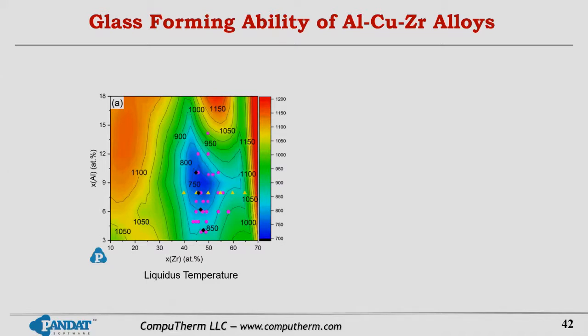Here, in this aluminum-copper-zirconium ternary system, we calculated the liquidus temperature for several hundred alloy compositions and presented the simulated results as a color map of liquidus projection, liquidus temperature. The solid points shown are compositions already identified experimentally as forming bulk metallic glass, and as you can see, they are all located in the low liquidus temperature region.